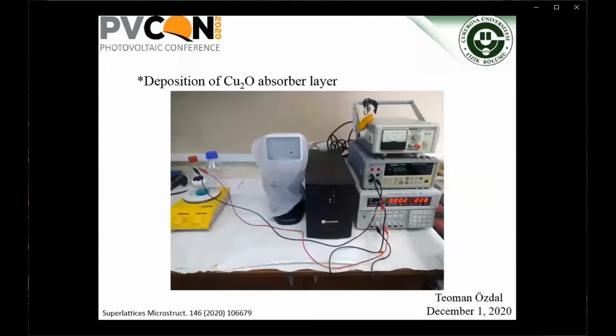We electrodeposited cuprous oxide layer onto zinc oxide with two electrochemical cells at 0.9 milliampere per centimeter square constant current. We used a simple DC power supply as current source and microammeter for manually controlled current density. Platinum sheet was used as counter electrode. Here is the cell, power supply, and microammeter.